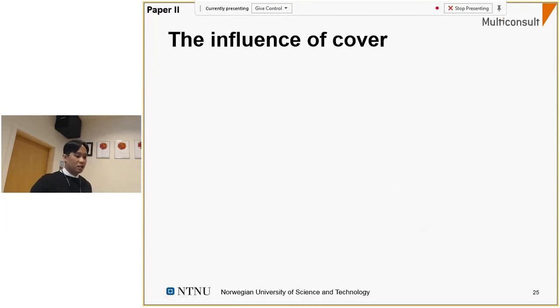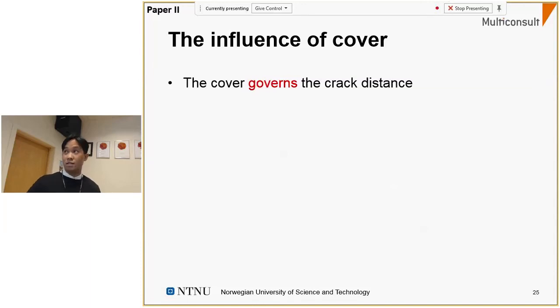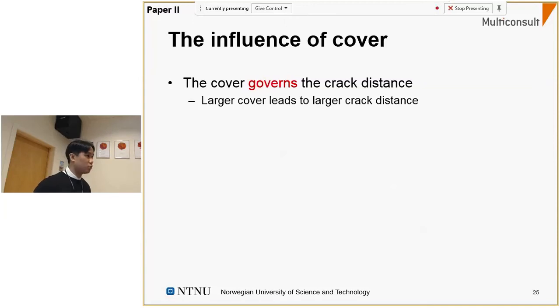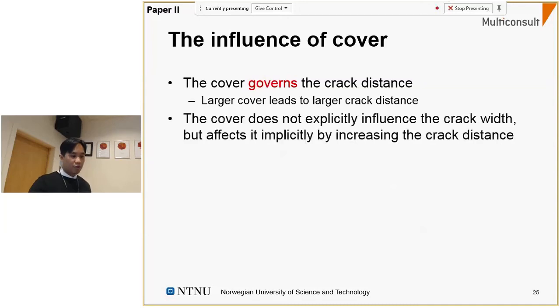Now, what we see is that the influence of cover is that the cover governs the crack distance. And larger cover leads to larger crack distance. So nothing new about this, nothing revolutionary. This has been seen in experiments and is also known by most common engineers. However, what we saw was that the cover does not explicitly influence the crack width, but affects it implicitly by increasing the crack distance. Now I will explain what I mean by this sentence.